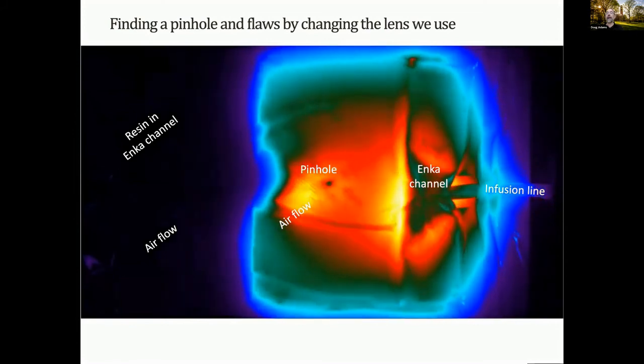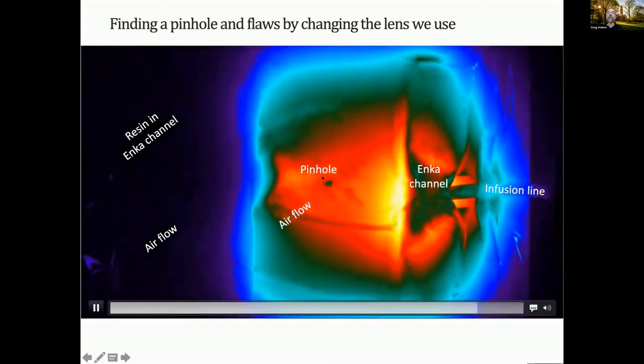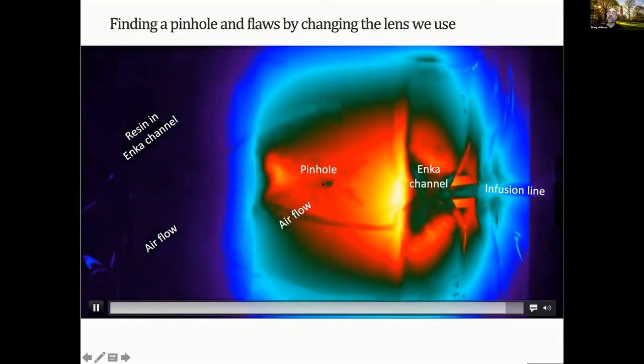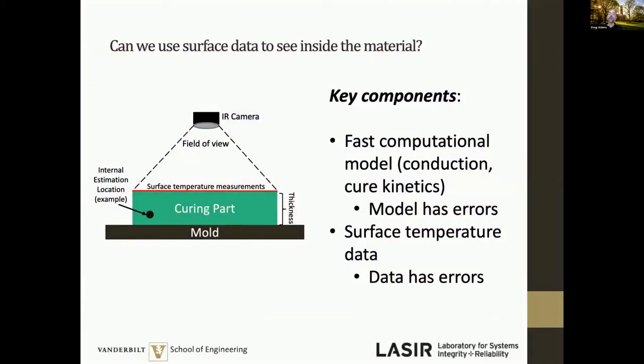But you might ask, there's the pinhole, how can you see things not just on the surface but deep inside the part? And so that's really what our technology addresses, is the idea of using that surface temperature combined with a heat transfer model to actually infer what's happening below the surface. And so what we do is we use a fast computational heat transfer model, an inverse model we call it, along with that surface temperature data in order to infer that there's a change, for instance, in the heat that's being emitted beneath the surface that might be indicative of a flaw.